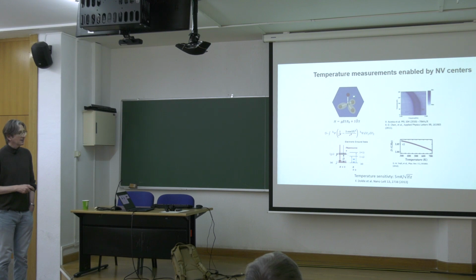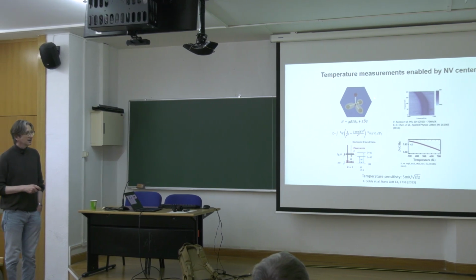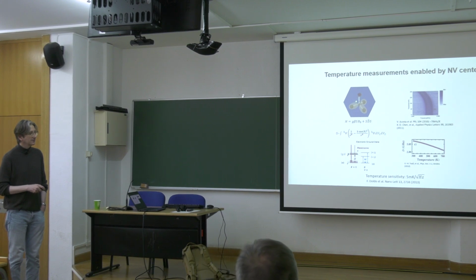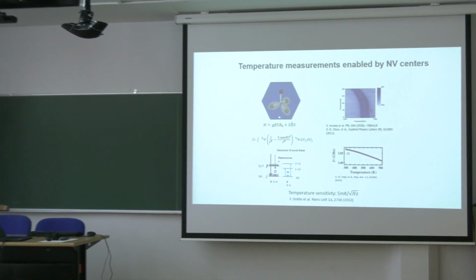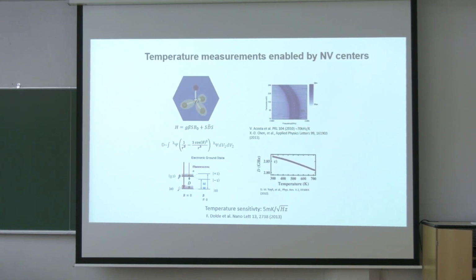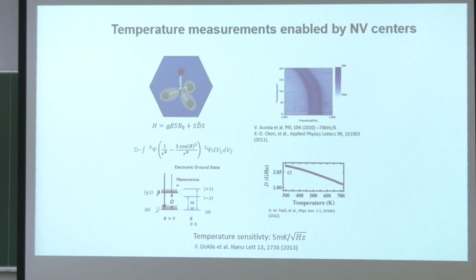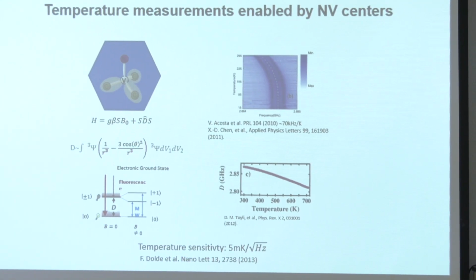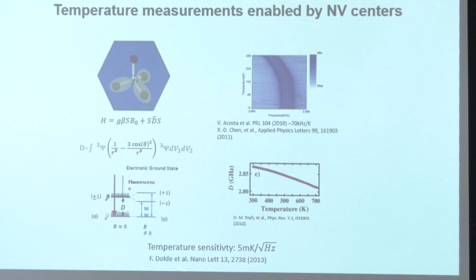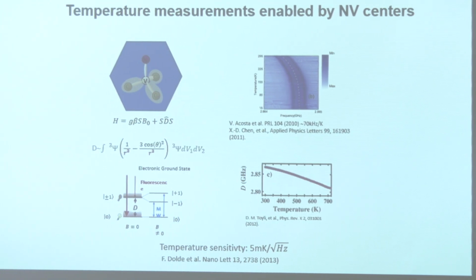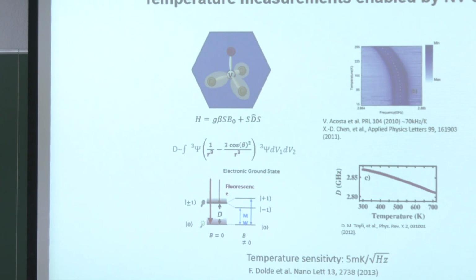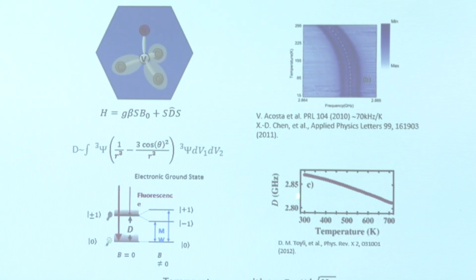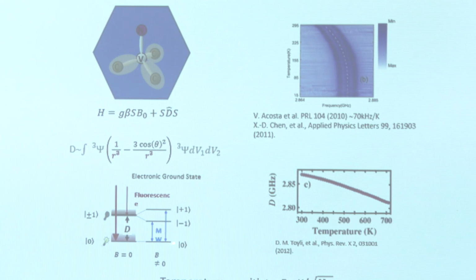The NV center has a wave function that is located around the carbons and the nitrogen. And because it's spin 1, there is a kind of intrinsic interaction between two electrons that creates the so-called zero field splitting. So even in zero magnetic field, the NV center states are separated by about 3 gigahertz. And this splitting depends on the confinement of the wave function. Now, if the temperature rises, the diamond lattice expands, and there is less confinement and less interaction between electrons. So that creates a dependence of the zero field splitting, the separation between 0 and the middle between plus and minus 1 states, as a function of temperature.